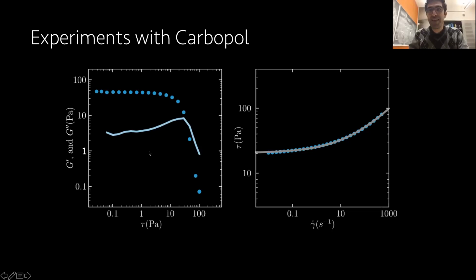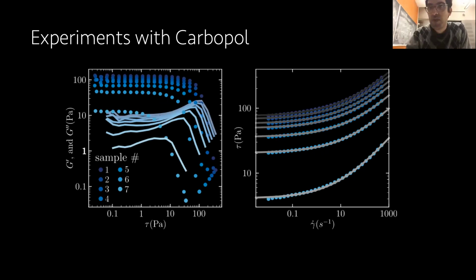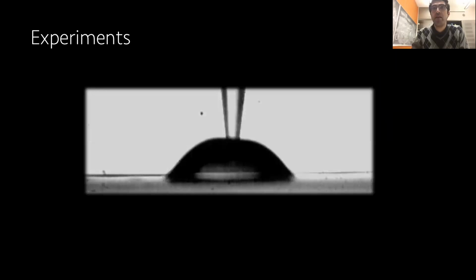On the left, I'm showing the elastic properties of Carbopol for a given concentration. As you can see, if the stress is low, your G prime, which are the circles here, is much bigger than your G double prime. So the material is more like a viscoelastic solid, with G prime being much larger. But as you put more stress, it starts to yield, and then both G prime and G double prime fall. Your material now looks more like a Herschel-Bulkley fluid, and you can get the flow curve. You can tune these properties by changing the concentration of Carbopol, and this is what we've done, and we tested many of them.